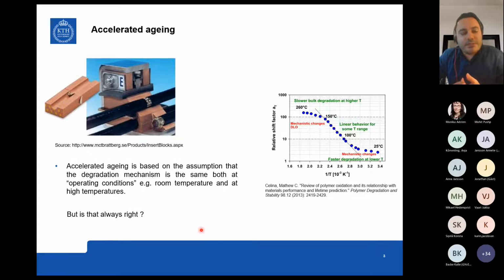And usually when we do accelerated aging tests, we base them very much on the assumption that when we do a high temperature aging or a high dose rate aging, the degradation mechanism at those extreme conditions is more or less the same as in the operational conditions. But you have to take that with a slight pinch of salt. As Anya showed also in her slides, at high temperatures you can get other phenomena, for instance, diffusion limited oxidation.